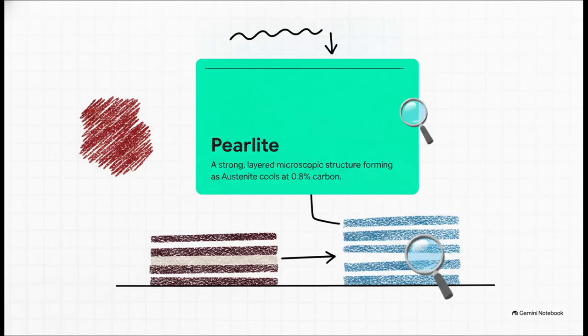When that hot red austenite cools down with exactly 0.8% carbon mixed into it, it transforms into a phase called pearlite. You can spot it mapped out in the bluish, stippled areas right below that 727-degree line. What's happening is it's alternating layers of soft ferrite and hard carbon-rich material. Under a microscope, it actually looks just like mother of pearl, which is where it gets the name pearlite. This specific layering gives the metal incredible strength, plus a very unique kind of flexibility that pure iron just completely lacks.